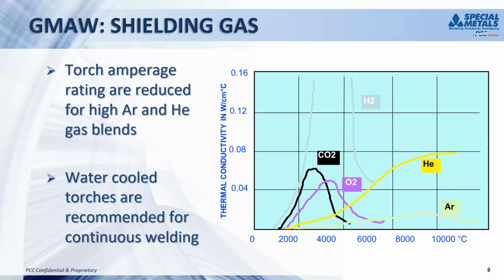The other second, probably largest problem I hear about is people complaining about burn backs on the tips. And what that really comes back to a lot of times is the type of shielding gas that's used for the nickel welds. Normally, we recommend as a safe catch-all 100% argon. There's argon and helium gas blends that work very nicely for different reasons.